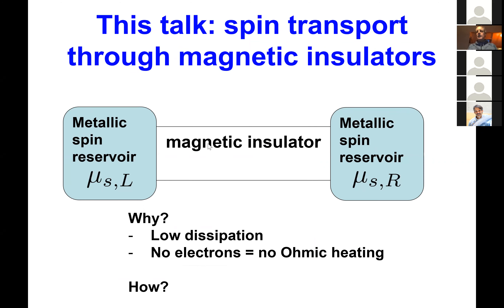In this talk I'll mostly discuss magnetic insulators connected to metallic reservoirs of spin. Magnetic insulators are interesting because they have very low dissipation of spin — the quality factor, meaning the number of precessions the magnetization can have before reaching equilibrium, is on the order of 10,000 or even 100,000. So there is very little dissipation, very little spin relaxation.